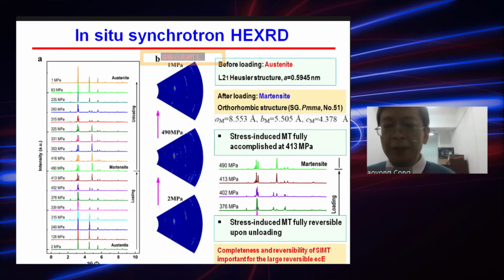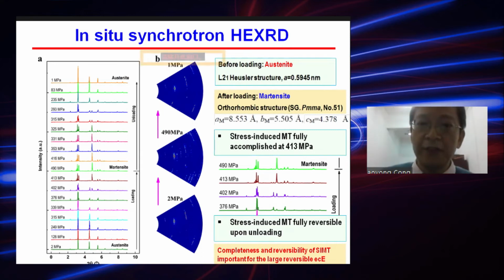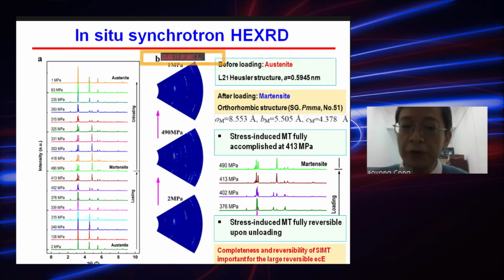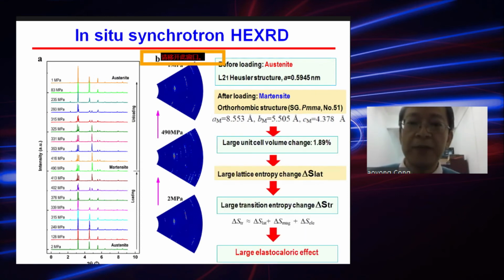The completeness and reversibility of the stress-induced martensite transformation is very important for the large reversible elastocaloric effect. If the transformation is not complete, we cannot make full use of the latent heat. If the transformation is not reversible, the elastocaloric effect can only be used once, not repeatedly.